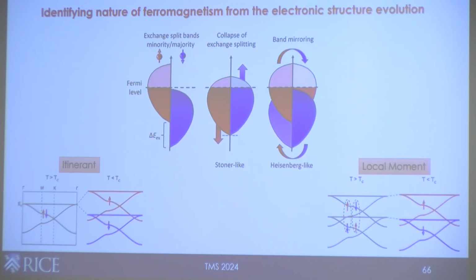So how do we actually learn about the nature of magnetic order from an ARPES perspective? I wanted to show you how we can probe this question: what is the nature of a magnetic order? As we have all learned, there are different ways to understand magnetic order, and these are the two extreme limits. You can have a Stoner-type itinerant origin of the magnetic order. Here, it's because of the high density of states at the Fermi level, which will spontaneously split into majority and minority states, giving rise to the magnetic order phase, and so give you the magnetization overall. What do you expect? You expect the spin splitting to happen right at the Curie temperature in this case.